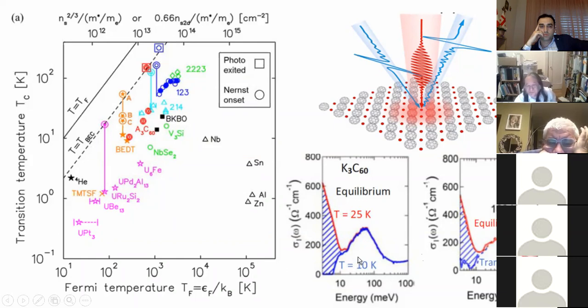And the same thing was also measured in the cuprate superconductor. So this is the case of cuprate. And as we will show you, after we found this correspondence, I encouraged Cavalieri to measure this organic BEDT superconductor, and they indeed found this transient-like superconductivity to start on this dotted line.